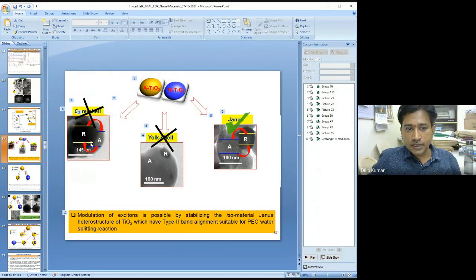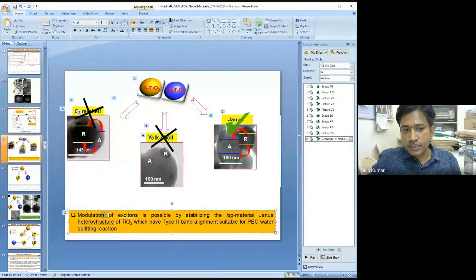with the band energy states, the electron hole pairs have been nullified or quenched. The same case with the yolk shell also, anatase and rutile band energetics will not favor it, except the Janus structure where the anatase rutile can be facilitated to be used by the species and used for the modulation of electrons.